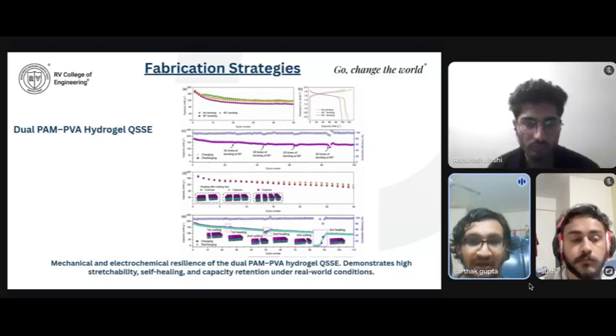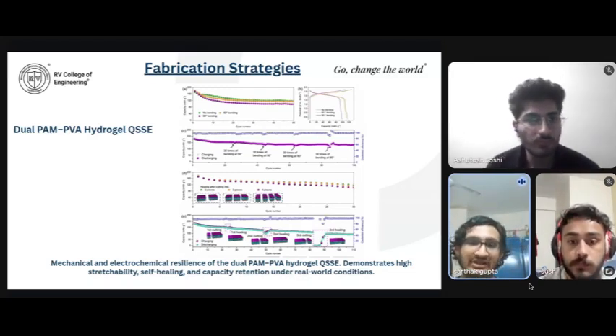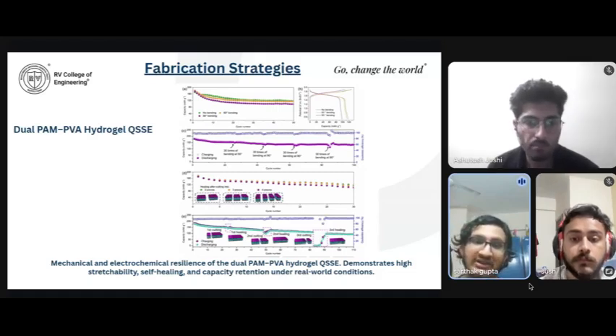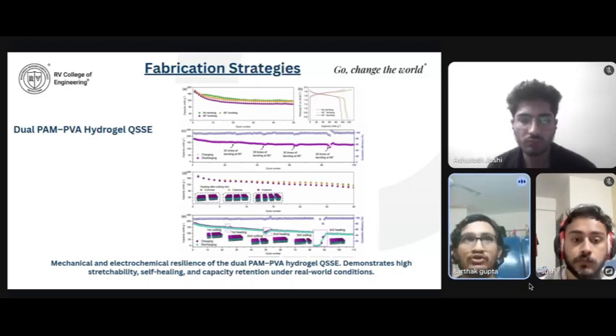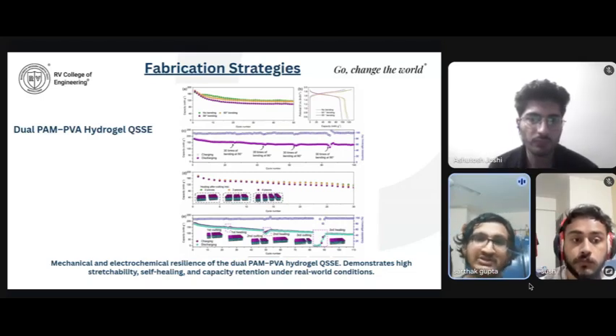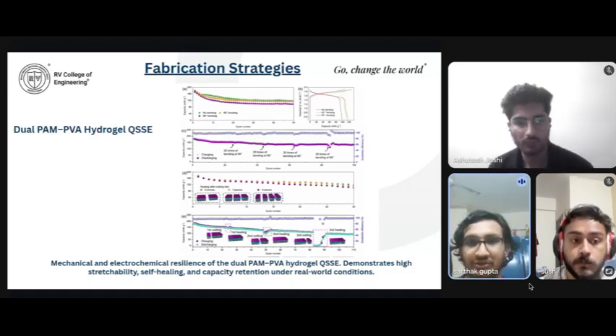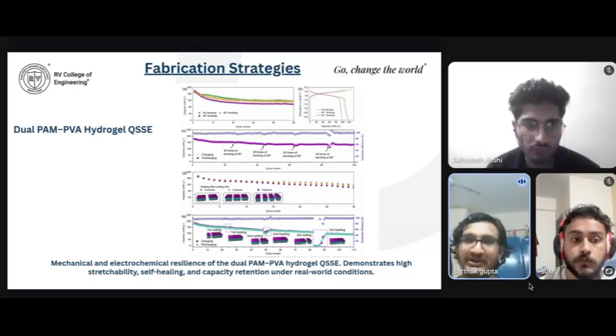Coming to the next part, which is the cutting and self-healing test. It's like a static test which the authors of the paper present. The hydrogel is cut into 2, 3, 4 pieces, then rejoined with adhesives. Remarkably, after healing, the battery recovers its electrochemical capacity, nearly matching the original performance. This proves that the hydrogel structure is physically reconfigurable and self-healing at room temperature, which is one of the most interesting parts and an area of interest which most people are looking into when doing all these QSSE things. With a property like self-healing in a battery, the efficiency of using the battery and the shelf life of the battery will obviously increase.